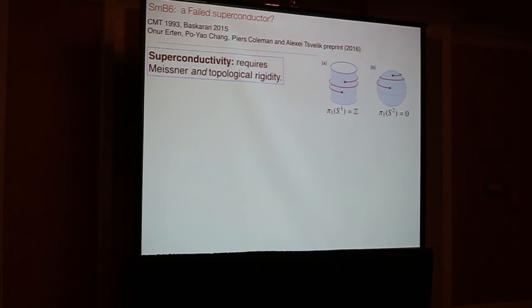A superconductor is not just a superfluid, it's a charged superfluid. And it has local gauge invariance. And our colleagues, the particle physicists, have long been telling us that we shouldn't think in terms of an order parameter, because there isn't one. Because if you imagine applying a pairing field to a superconductor and now slowly removing that pairing field, unlike a ferromagnet where you stay in the polarized state, in a superconductor, Elitzur showed a long time ago that as you remove the pairing field, it averages over the full orbit of the superconductor, and you have no order parameter left.